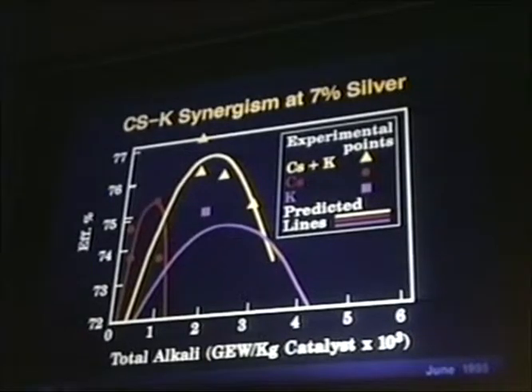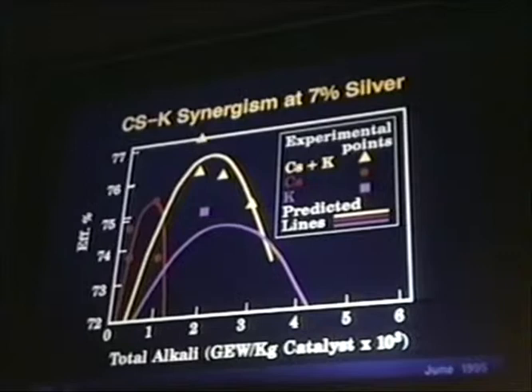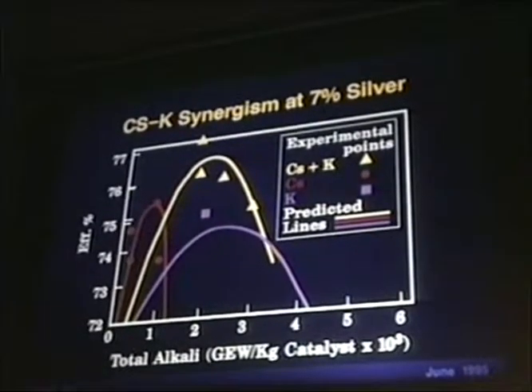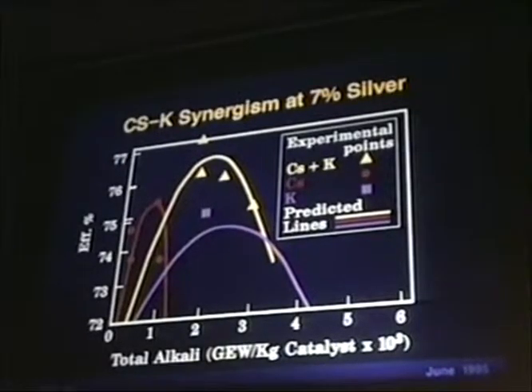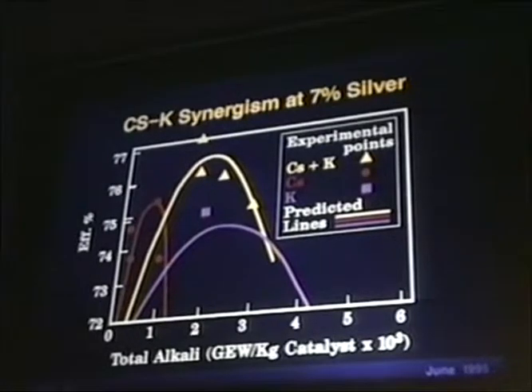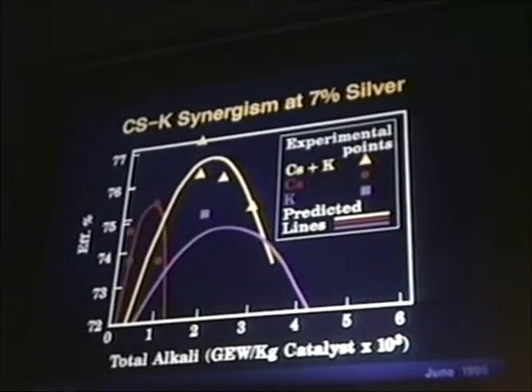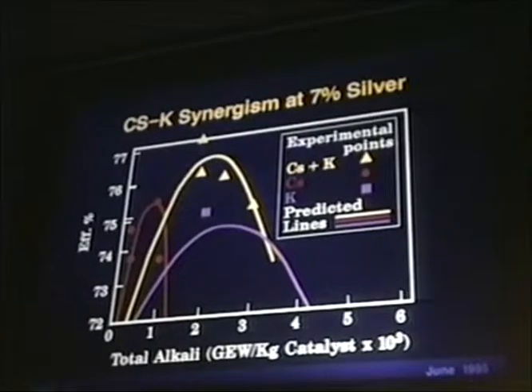But I share with you the performance of the cesium-potassium mixture. On the left is the cesium-only catalyst, which gives an efficiency of 75.5% at a total alkali content a little below 1 gram equivalent weight per kilogram of catalyst. And also you can see a very sharp optimum. Potassium, on the other hand, has a very broad efficiency maximum around 74%. However, you will note the mixtures of cesium and potassium have an efficiency that is higher than the best cesium can do, which is by itself the best alkali promoter individually.